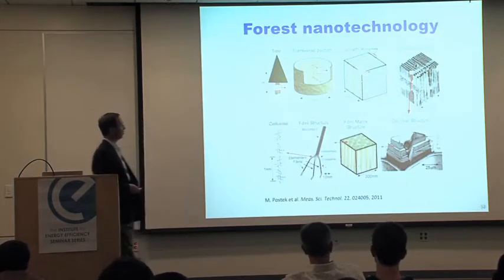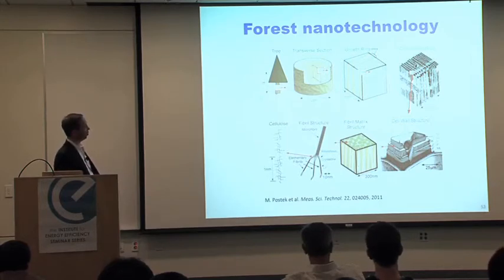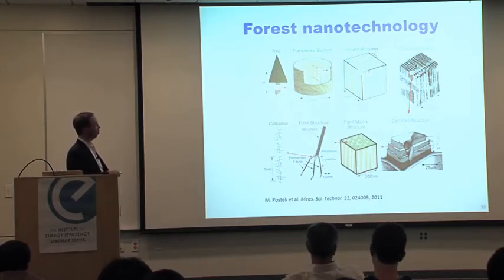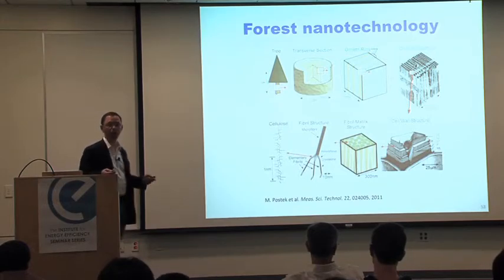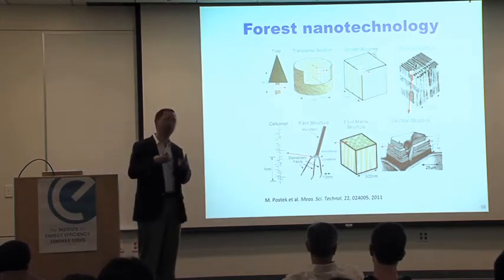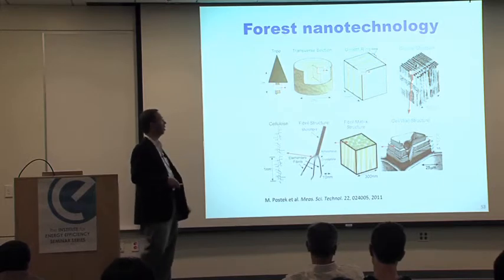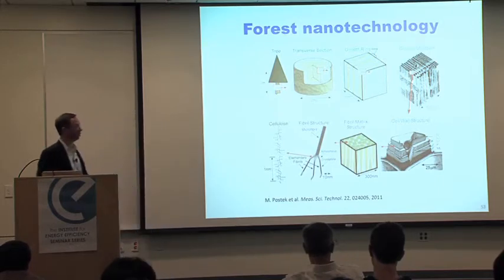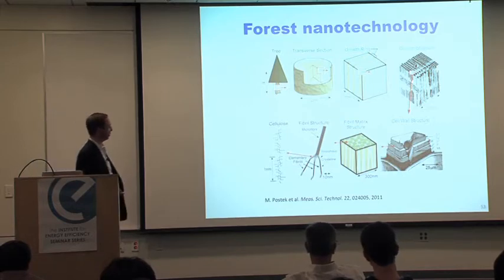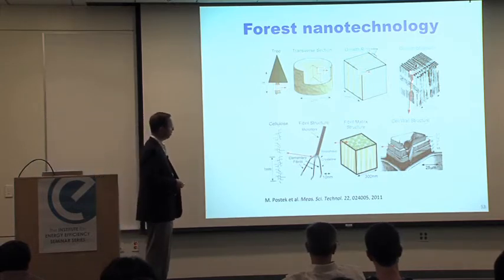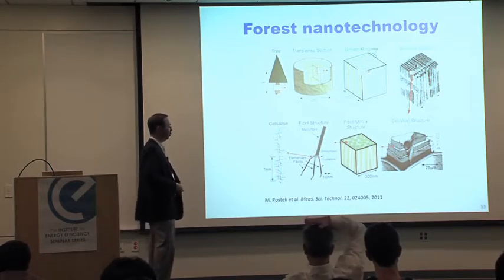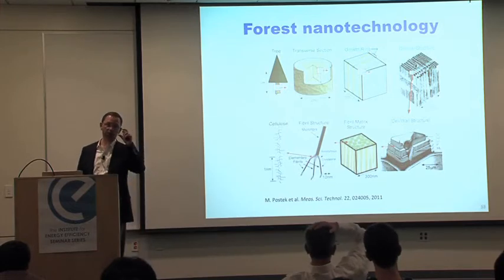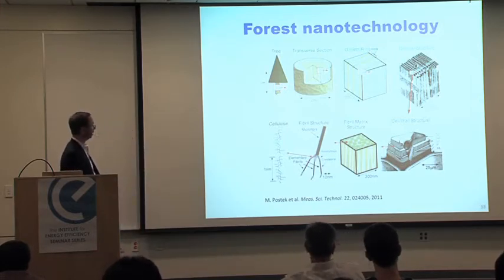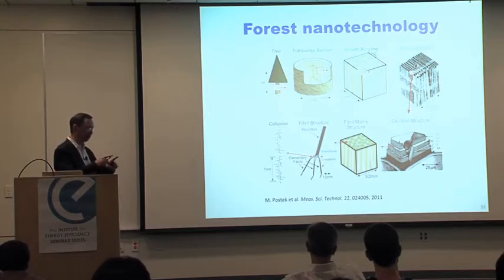And the answer was cellulose. And so you're all familiar with the process by which you transform wood into paper pulp and make paper from fibrils, but paper is fairly rough and it's difficult to fabricate solar cells and printed electronic devices on top of paper because of that roughness. But if you go a few steps further and you break down paper pulp, you can break it down into these cellulose nanocrystals, which are a few hundred nanometers in length and a few nanometers in diameter. And these can form films and solids through hydrogen interactions.